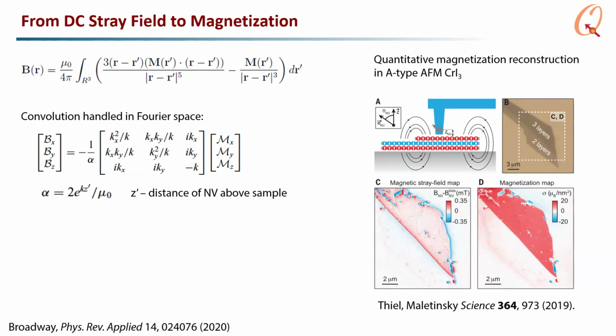Okay, so how do we go from measuring a stray field to a magnetization? Well, the stray field just comes from an integration of the magnetization over the sample surface. So that's just given by the dipole moment, and it's a convolution over the sample volume. So these convolutions can be handled in Fourier space, where if I measure the stray magnetic field, the Fourier components of that stray magnetic field are directly related to the Fourier components of the magnetization. However, you'll note that this matrix that relates the magnetic field in Fourier space to the magnetization in Fourier space has rows that are linearly dependent, and it's not actually invertible. So you'll see that the second row is just the first row multiplied by ky over kx. So this means we can go from magnetization to magnetic field, but we can't go backwards uniquely without assumptions.